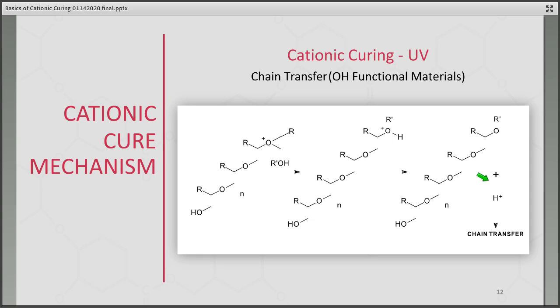Okay, and we're missing some of the bonds here I see on this. This should be a polymer connected. But you can also have, in this process, a chain transfer reaction when you have a hydroxy functional material. So in this case, and consider it should be a straight bond here, it reacts with an alcohol, and that will tend to terminate this polymer chain and transfer over to another polymer chain. So you get classic, in polymerization, a classic chain transfer reaction. And this is where you can build up shorter chain polymers.